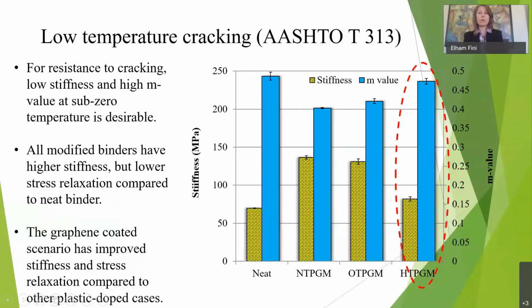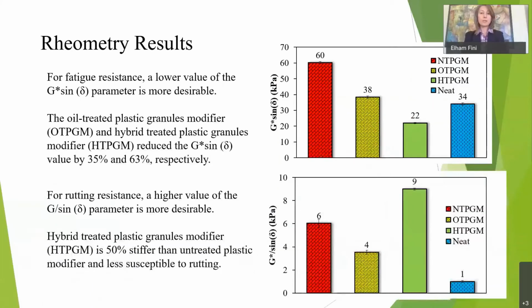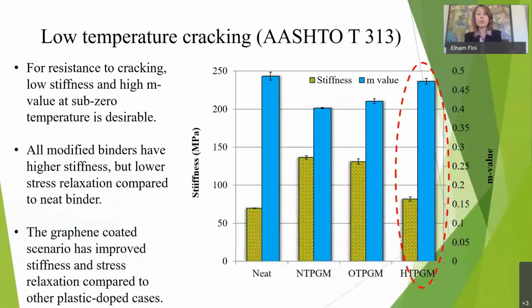Then you can think, okay, you talk about all this rutting, fatigue, and whatnot in regular temperature, like a regular day, maybe a summer season or whatnot. What happens in a very cold season, like winter in Minnesota? What about that? Does the plastic make the road crack more or less? So we have another test for that, which is actually for sub-zero temperatures. Here we test the sample at -12 centigrade. And we measure their stiffness.